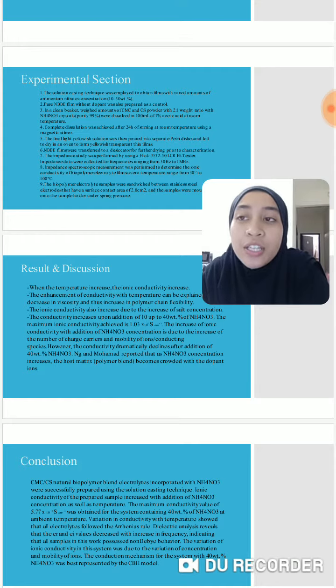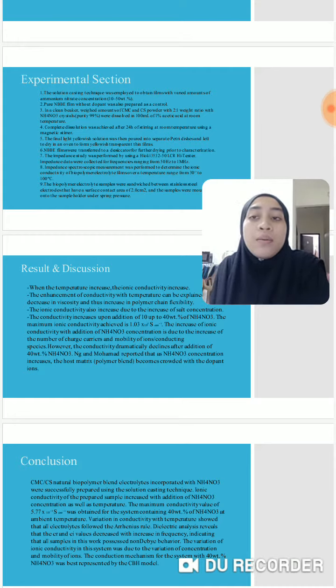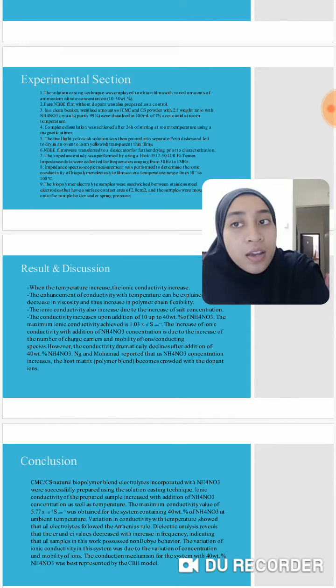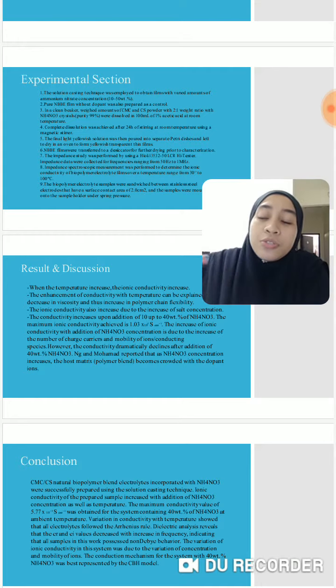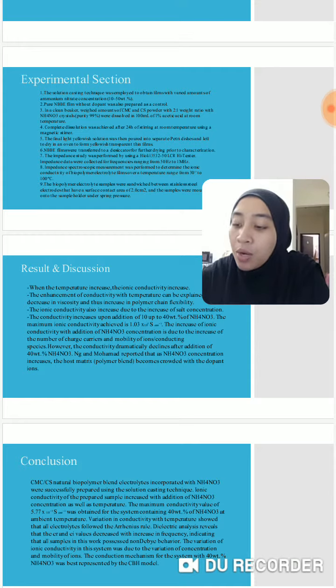The increase of ionic conductivity with addition of ammonium nitrate concentration is due to the increase of the number of charge carriers and mobility of ions or conducting species. However, the conductivity dramatically declines after addition of 40 weight percent of ammonium nitrate. Ng and Muhammad reported that as ammonium nitrate concentration increased, the host polymer blend matrix becomes crowded with the dopant ions. Because of that, the conductivity declines. This report also comes from the Ng and Muhammad journal.